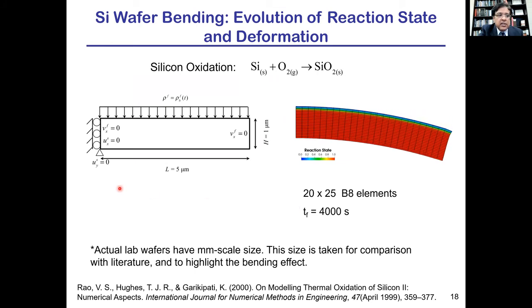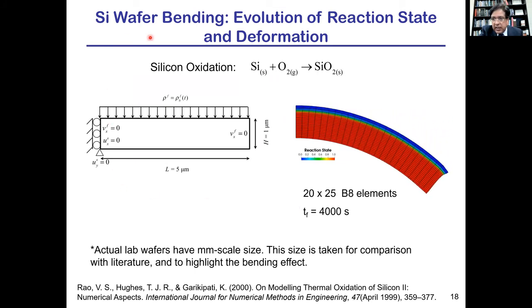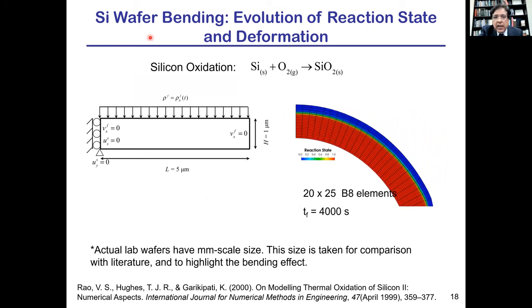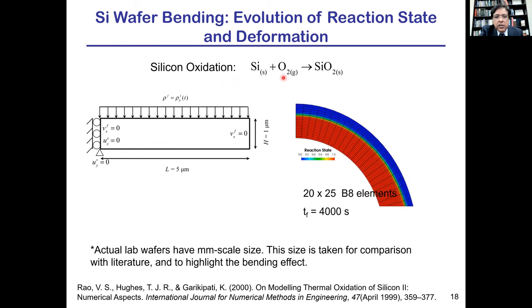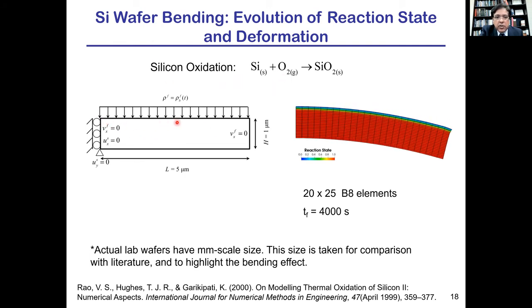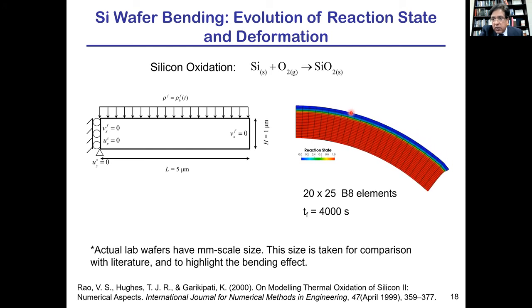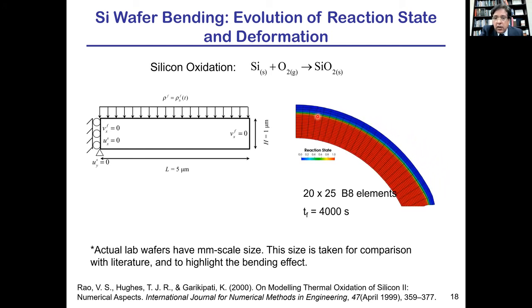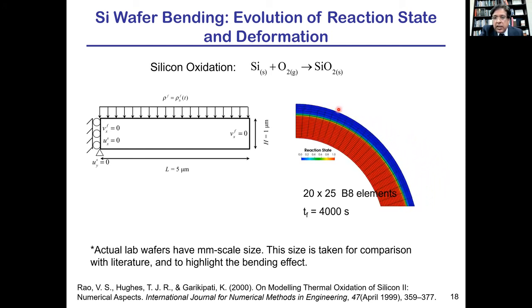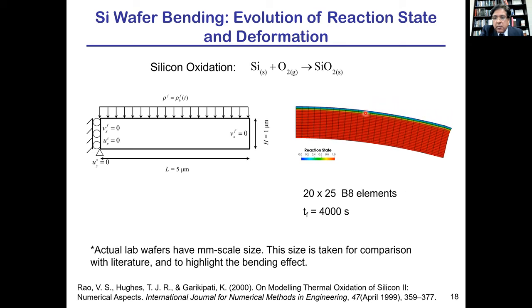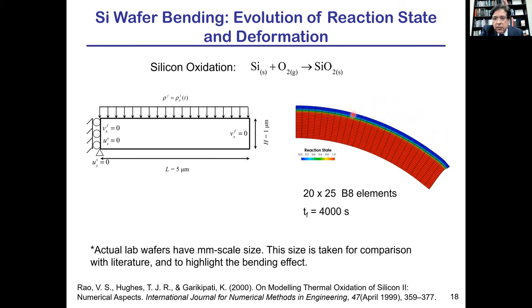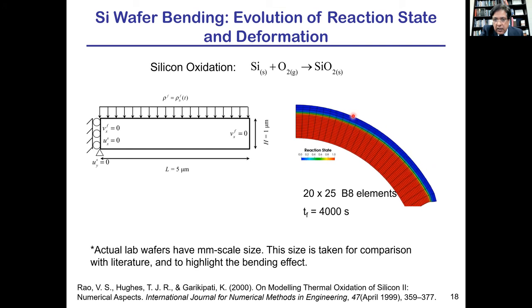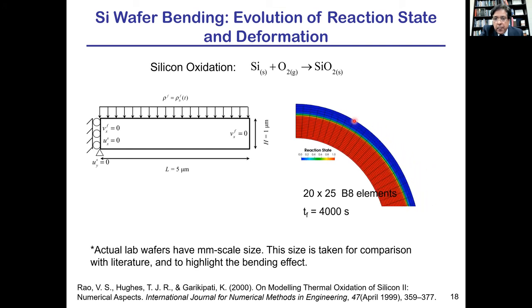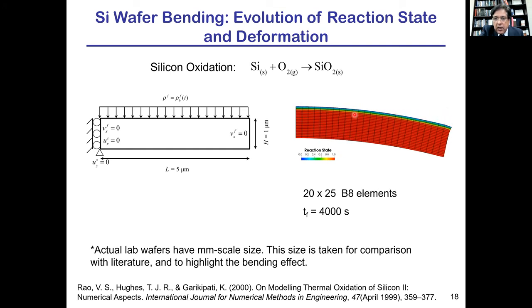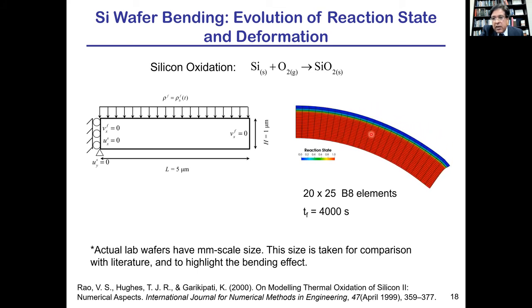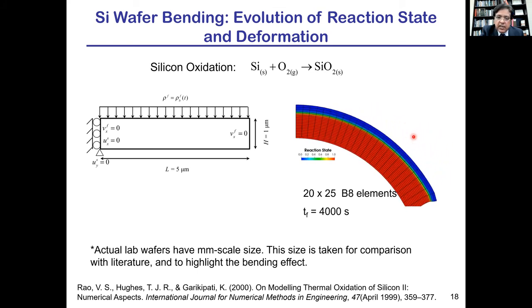The next numerical problem is a silicon wafer bending problem, typically in electronic structure modeling. It's again silicon reacting with oxygen. The top surface is exposed to oxygen, and it expands. Expansion is about two times the original volume, so there is a substantial change in length at the top. Since the material is contiguous, you can see the reaction front moves from the reacted into the unreacted zone. This yellow line moves down. Because of this, a local bending moment is produced, giving rise to this large deformation.